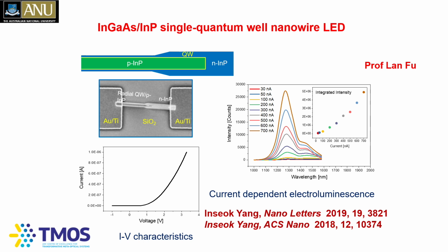After growth, you transfer them onto a glass slide, do electron beam lithography, and put on some metal contacts to inject current so that you can get the light emission. You can see the IV characteristics showing diode-like behavior, showing that the hard work of Inseok has paid off. Then, as you inject more and more current, you can see brighter and brighter light coming out. You also see two emission peaks, because the quantum well sitting here in the axial direction has a different composition and thickness than the sidewall ones.